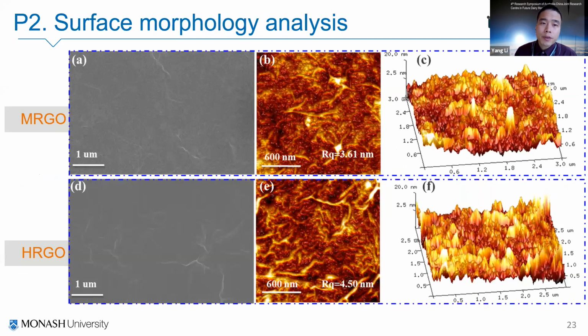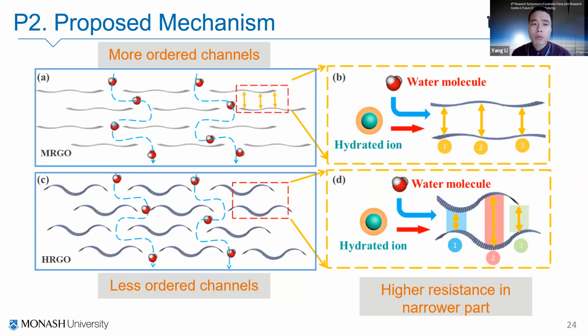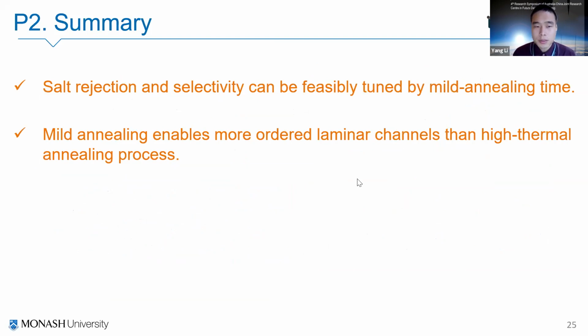And we used surface morphology analysis, and we found the high thermal treatment membrane shows a more wrinkled structure with a higher roughness. So basically we attribute the different separation mechanism to the more laminar channel that is stabilized in the mild reduction process. In such more ordered laminar channels, the water can permeate the membrane with less resistance. So the membrane shows a higher water flux, and the more ordered laminar channel also enables a precise sieving effect towards hydrated ions. So we achieve a higher selectivity. So this is the summary of part 2.